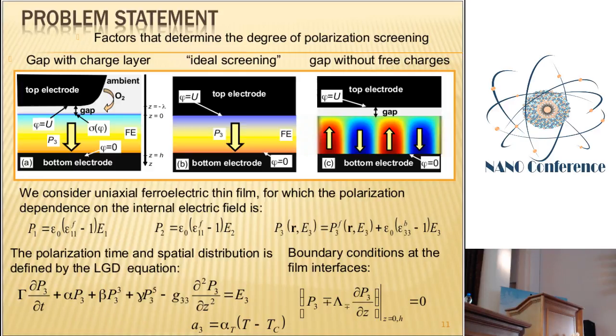It is the usual representation for the components of ferroelectric polarization. The in-plane components are described by a linear relation with the external electric field, and the component perpendicular to the film surface is the ferroelectric component, and this component obeys the nonlinear Landau-Ginzburg-Devonshire equation with cubic or fifth order nonlinearity. It depends on the transition order in the ferroelectric. The boundary conditions are of the third order, and these conditions are typical for ferroelectric thin film physics.